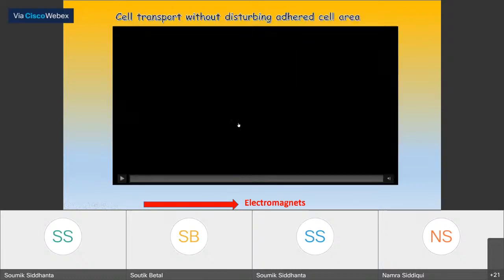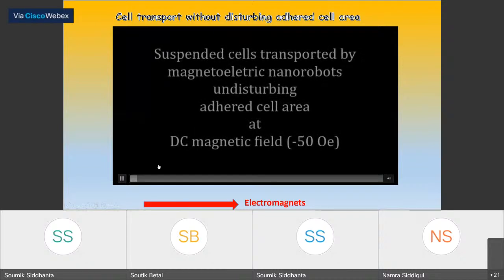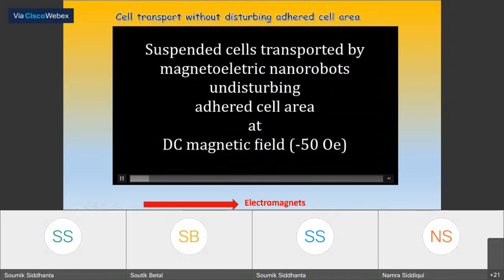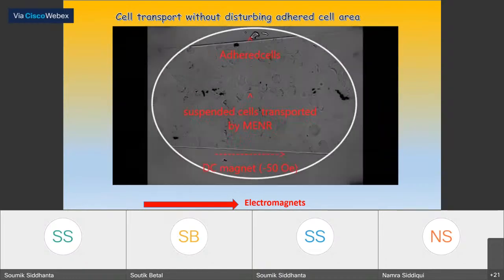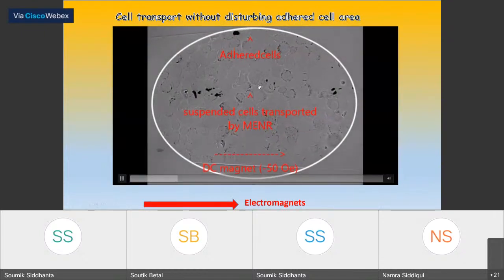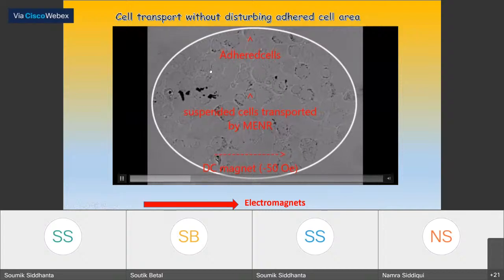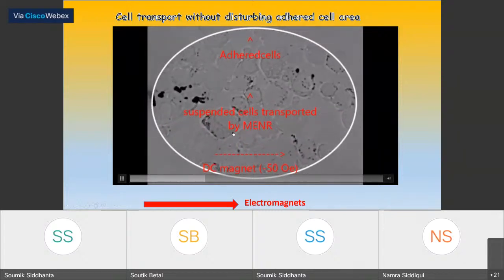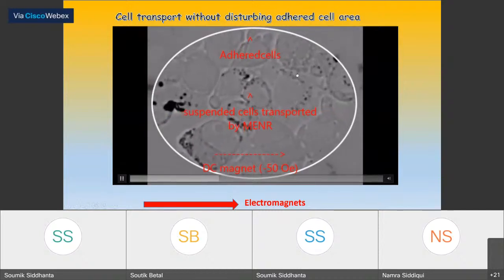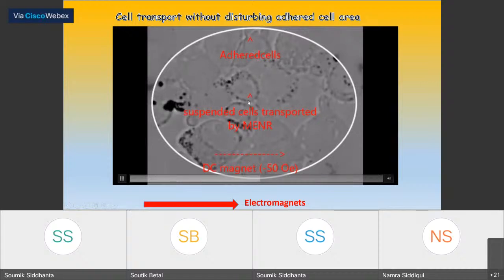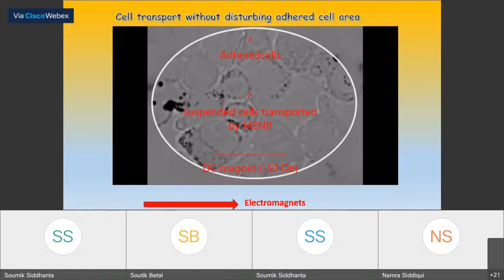Yes. So next is the higher magnification video where we have targeted some suspended cells using the robots, and then try to move these suspended cells using the magnetic field through an adhered cell area without disturbing any of the adhered cell area on the pathways. Here you can see that the robots are on the cell membrane, and they are pushing the cells through these adhered cell areas in a very controlled fashion without any disturbance to the adhered cell areas. That means if we have nerves in the areas, it will not disturb the cells of the nerves. Rather, it can pass over these suspended cells in a very controlled way.